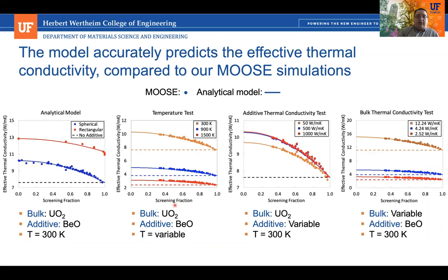But we wanted to test this in other conditions. So the first thing that we did is we changed the temperature. We still used UO2 and BeO, but we looked at 3 different temperatures: 300 Kelvin, which is of course the result here, 900 Kelvin and 1500 Kelvin. And these are just for the spherical particles. And the dashed line in all these cases is the pure UO2. So what we can see here is that, again, the model compares very well. And we get a great comparison.